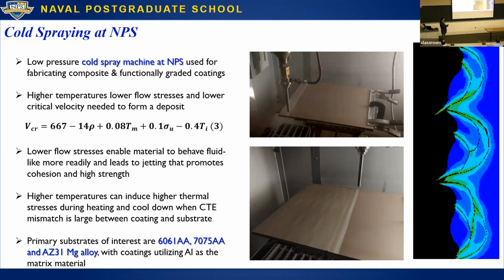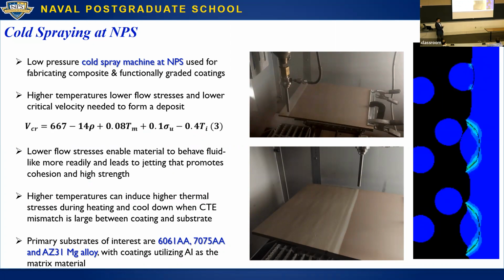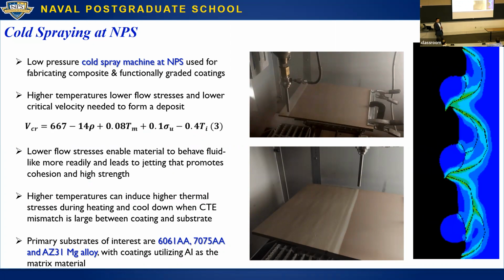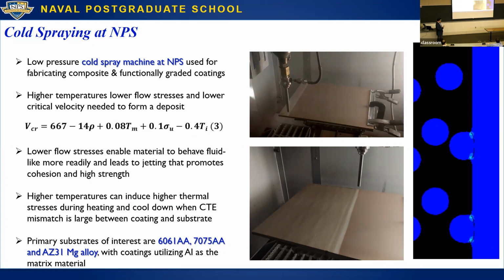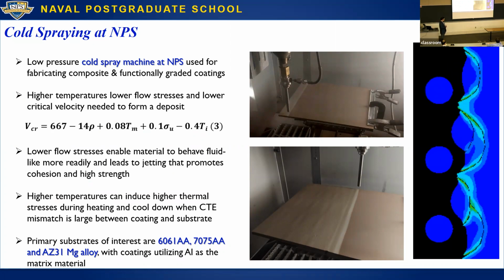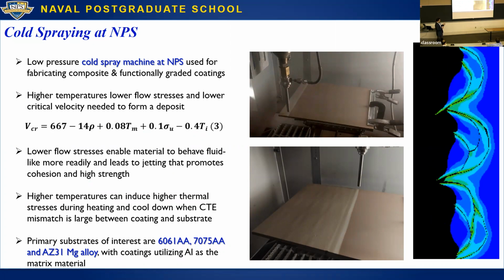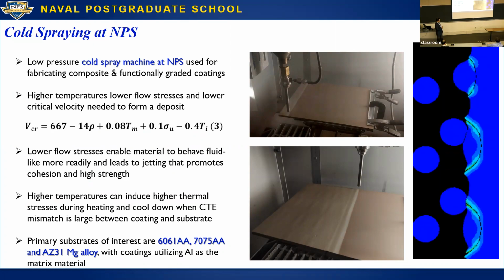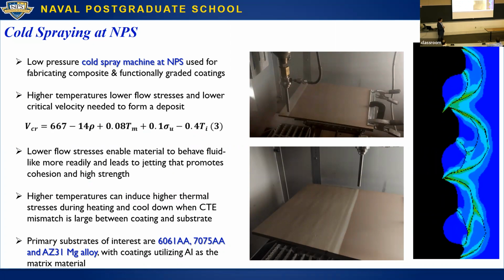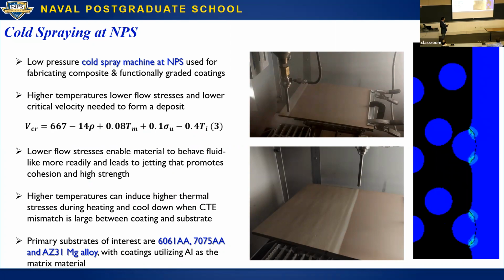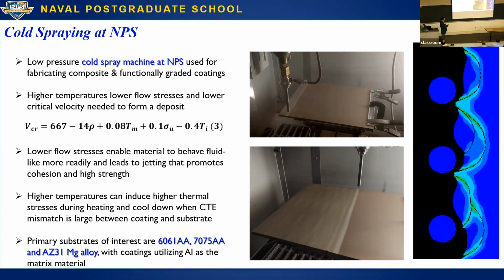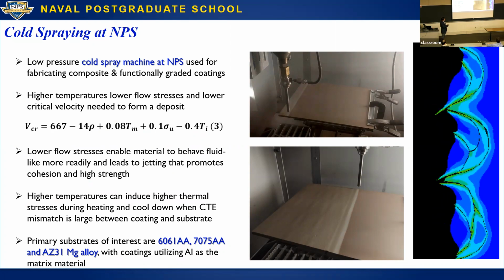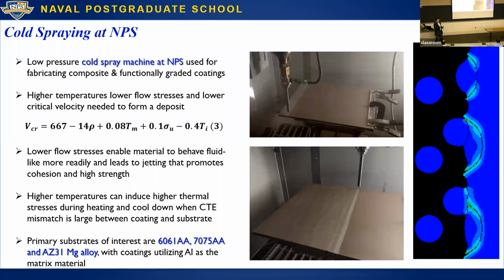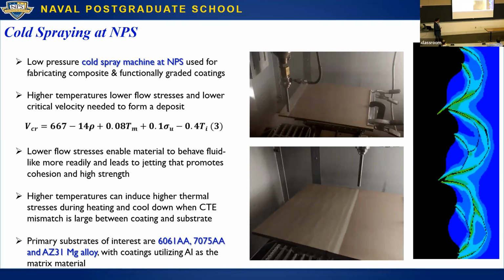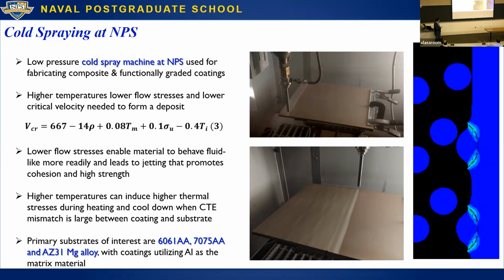Your particles impact the substrate, and there's actually some mixing that goes on there with the substrate, which is quite interesting. And we're making use of this approach when we make composites designed to get better adhesion, for example. One of the things we're doing is we decorate these particles with nanotubes, and now when they impact the surface, you're going to have nanotubes essentially bridging those interfaces that you see there, and we actually can get better adhesion there.